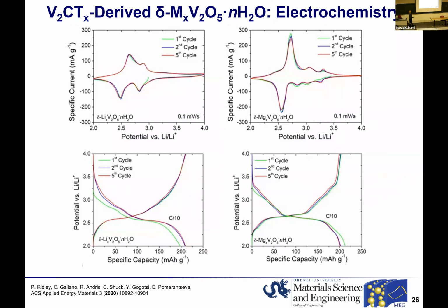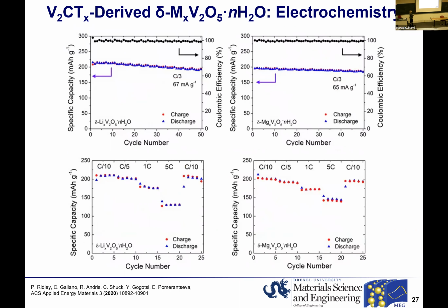And interestingly, through electrochemical cycling, we selected only lithium and magnesium pre-intercalated phases for cycling in lithium-ion cells, because those are the two materials that showed the best performance in case of alpha V2O5 derived bilayered vanadium oxides. One thing that we noticed is that the shape of the CV curves looks very different, which again implies that the charge storage mechanism in lithium pre-intercalated and magnesium pre-intercalated materials is different. But more interestingly, the electrochemical stability that we achieved for the MXene-derived chemically pre-intercalated bilayered vanadium oxides is still the best in the literature. No one else was able to show such excellent electrochemical stability for this class of materials. So that was a very exciting result.